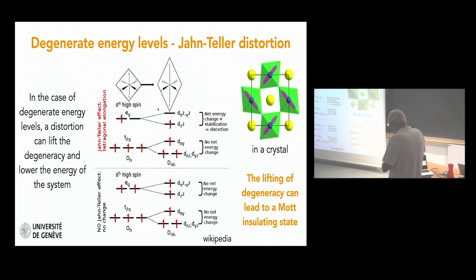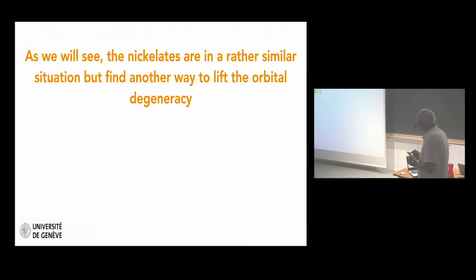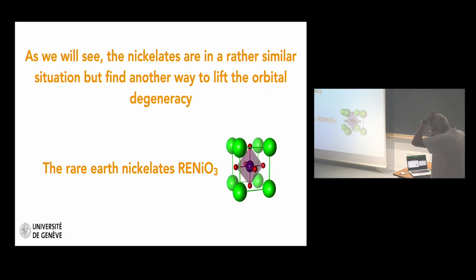But now, if you have a d5 system, still high spin, three spins here, two in the eg, this way this Jahn-Teller distortion doesn't help. So the Jahn-Teller distortion will occur for the d4, but not for the d5. And now the important thing is that when you lift the degeneracy, you end up with a system which is half-filled, and you can eventually go to a Mott insulating state. So as we will see, the nickelates are in a rather similar situation, but they find another way to lift the orbital degeneracy. So let me describe now these rare earth nickelates.